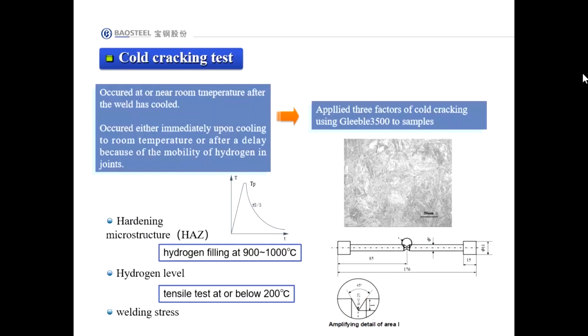Last one, but not the least, is to analyze the cold cracking tendency. Applying three factors together to the samples, namely hardening microstructures, a certain amount of hydrogen, and welding stresses, we can get some data about cold cracking sensitivity for various steels. Because cold cracking is very important for us, there are a lot of experiments we can use to evaluate it. So the physical simulation is just one of them.